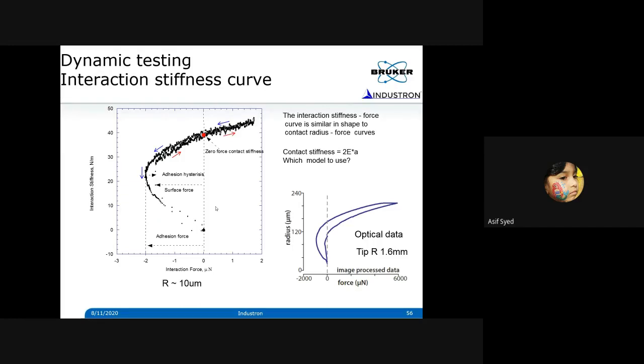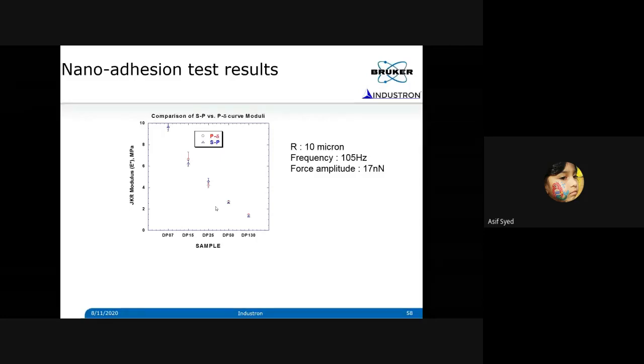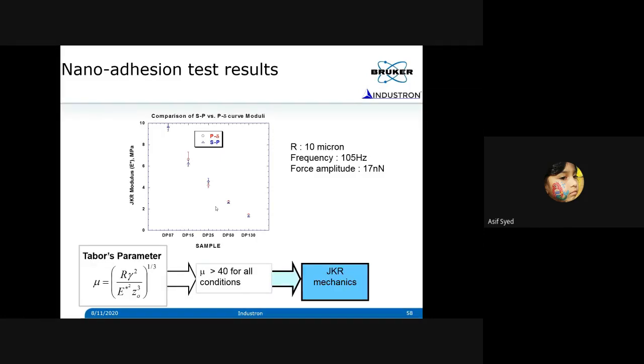Here, you don't have to worry about where the tip is making contact because everything is captured in this stiffness measurement technique. You just have to fit the curve and get the modulus of the material. So the worries about where we are making contact, where our zero point is, those things you don't need to worry about. Using this technique, we were able to measure and compare it with other techniques that work very well.